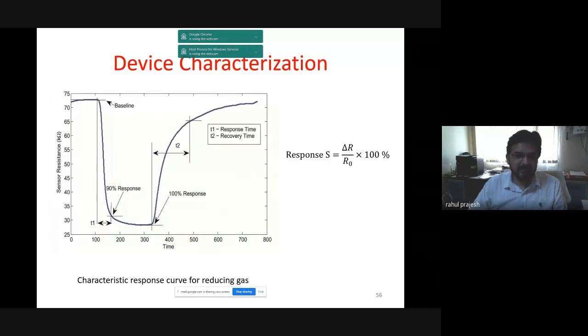So this is a typical curve of gas sensing, which I have observed. So initially, this is the resistance when there is air. Then you apply air with the target gas. You see, as soon as this is applied, the resistance falls, gets saturated, and once this is again removed, when you apply only air once again, the recovery starts, and it gets completely recovered.